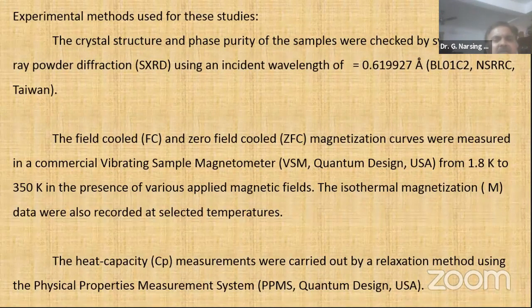Okay, so there is magnetic measurement. We have a vibrating sample magnetometer, Quantum Design. You can go from 1.8 K up to 350 K, or 700 K also. There is isothermal magnetization up to 9 Tesla that we can measure. There is also heat capacity measurement, that is the Physical Property Measurement System. So we can get very good thermal properties like resistivity as well as heat capacity. Using these methods we studied these materials.